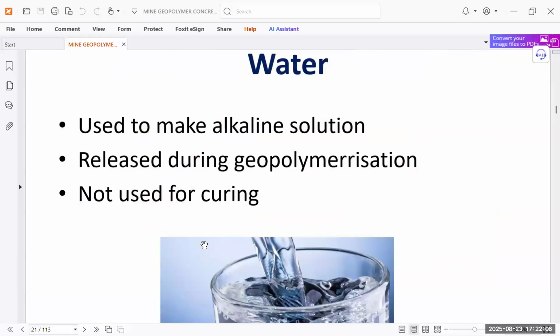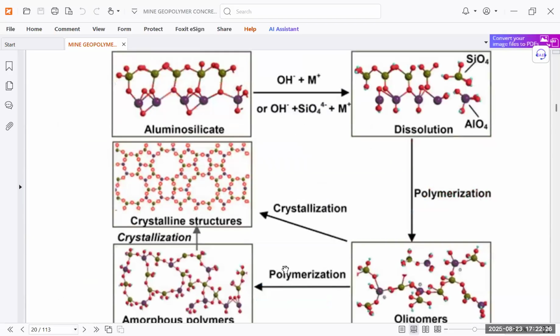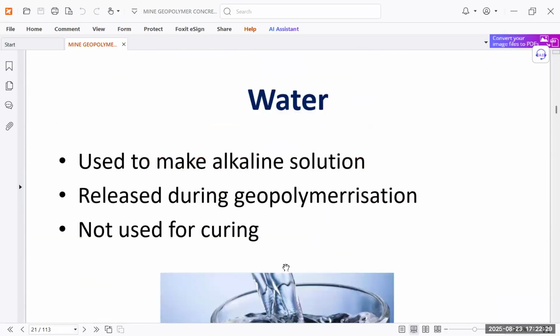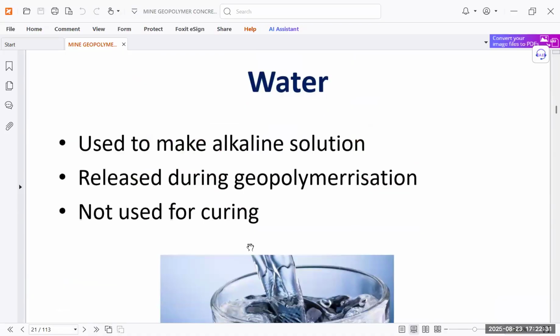So then why is water used here? Because you know that in OPC cement we use a water and cement mixture, so exothermic reactions go on. While here, still water is used. Now water here is used for making the alkaline solution, and it is released during geopolymerization. This geopolymerization is going on, so it is released during geopolymerization, and it is not used for curing.